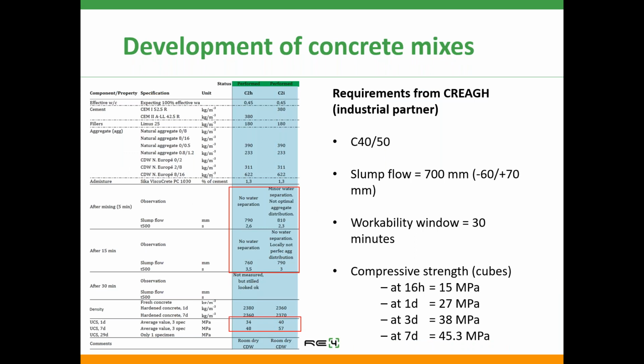So as an example, to the right, you see the requirements from CREAGH on the final strength class of the concrete, the slump flow of the fresh concrete, and it should keep this workability up to 30 minutes after mixing, and also this strength development. As Ruben mentioned, after 16 hours, they need 15 megapascal in order to demold and lift the elements. So here we show two different mix designs from the screening test and their properties in terms of slump flow, workability, and also compressive strength the first week.